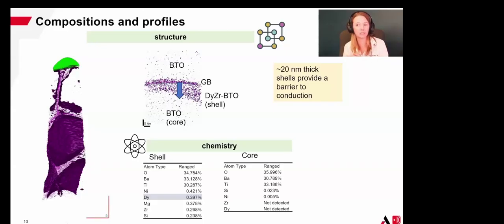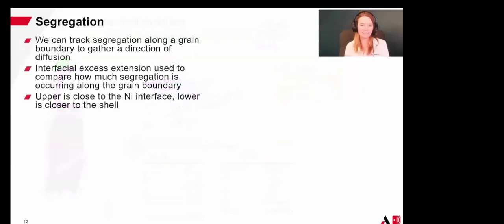So in this case, it's a good thing that we observe that, because that's telling us that our cores are relatively insulated as ferroelectric regimes from the paraelectric regime of the shells. The other thing that we see a ton of in off-the-shelf MLCC materials is grain boundaries. And I have to tell you, this research is so much fun because we have the presence of multiple phases, grain boundaries, and all kinds of stuff going on. So it's really a playground for material science.